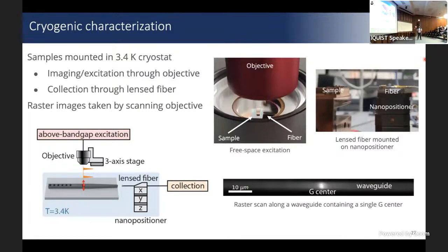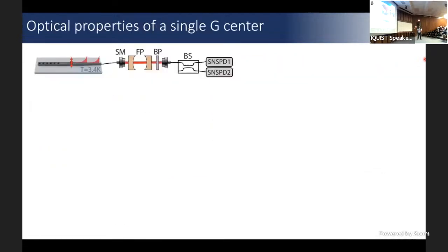And then if we take a raster fluorescence image of this photonic waveguide, in some of these structures we can indeed see just a single atom, a single defect that's emitting single photons into this waveguide. Also, let's look at some of the optical properties of these emitters in silicon. In this experiment, we basically do analysis on the photons that are coming out. We collect light into a single mode fiber.